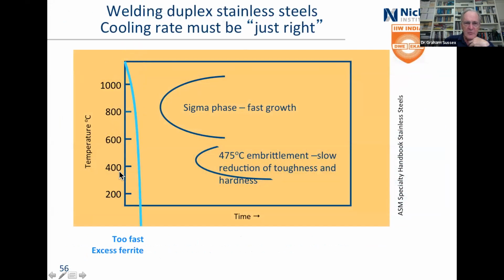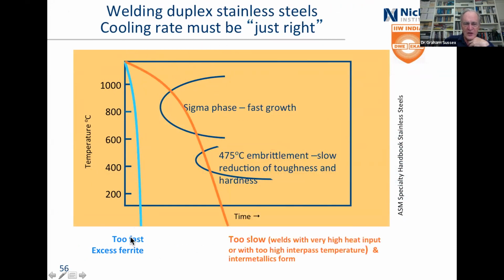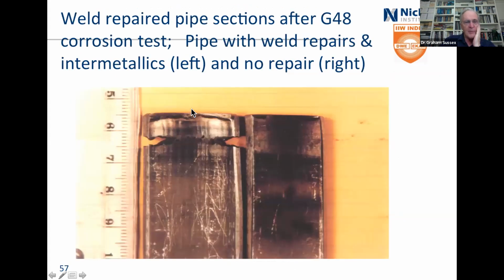If you're looking at high level duplex stainless steels, then if you cool them down too fast, you get too much ferrite. If you cool them down too slowly, you wind up with all sorts of intermetallic phases and you get corrosion, and that's not right. This bit is where you can get all sorts of galvanic effects, and I'm talking sigma phase and so on. This is an example of what happens if you have bits of pipe and people welding them improperly, and you get weld repairs, and then you put them in a test solution, which is a G48 test, ferric chloride. The ones that had been weld repaired looked like this. This is where the weld was, and this one had not been weld repaired, and it looks beautiful.